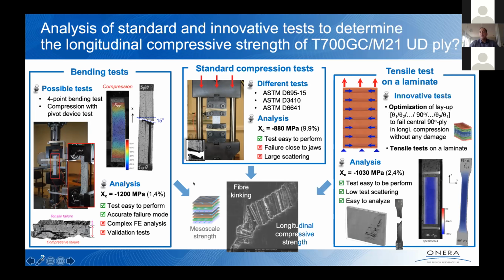And to finish, I'm going to present you a test which is really dedicated to composite materials. The idea is to perform a tensile test on a laminate with a very specific stacking sequence in order to measure the compressive strength. The main idea consists in testing a layup containing a central 90-degree ply. Due to the Poisson effect, you are going to generate longitudinal compression into the central 90-degree ply. And using an optimization algorithm, you can define the orientations of the other plies around in order to avoid any damage prior to the final failure, which is due to the longitudinal compression of the central ply.